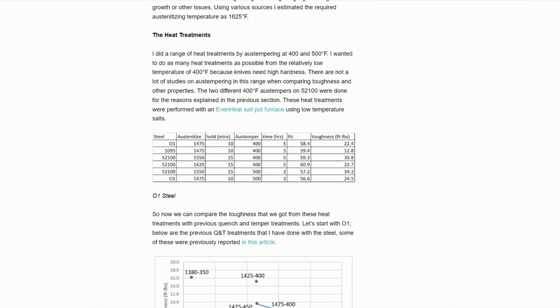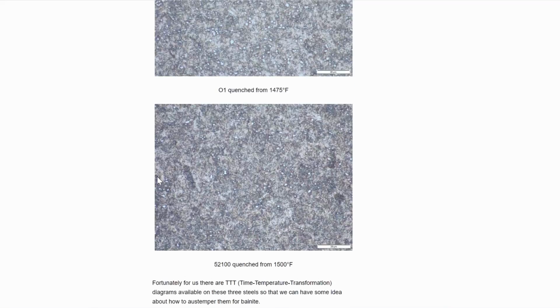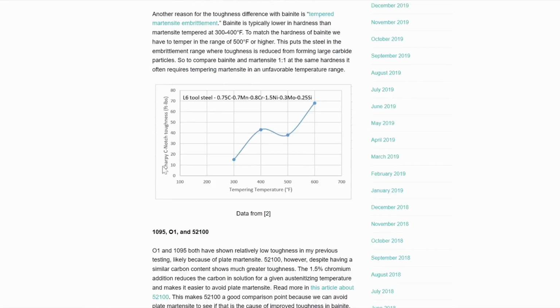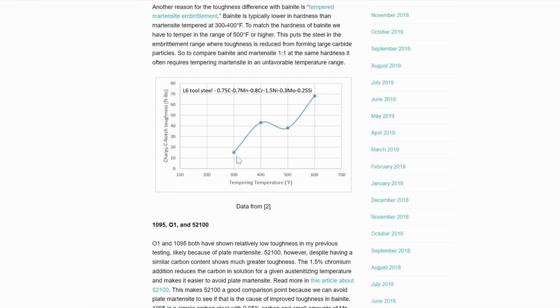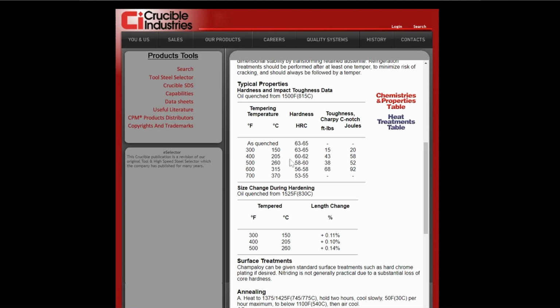The reason it does this is because martensite has an issue called tempered martensite embrittlement. This is L6 tool steel, and you can see if you increase the tempering temperature, the toughness goes up, but then when you increase the tempering temperature to 500 degrees, the toughness actually went down. And the hardness would also be going down. Looking at the data sheet for L6: 64 Rockwell, 15 foot-pounds; 61 Rockwell, 43 foot-pounds; but then 59 Rockwell, 38 foot-pounds. So the hardness went down and the toughness went down, which we don't want. It would be better to temper at 400.